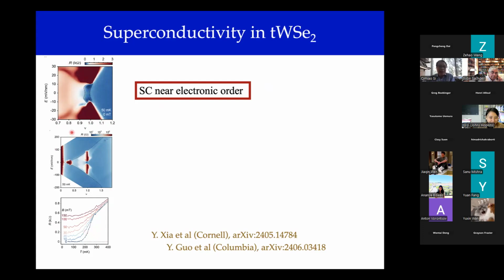And if you zoom out to a bigger phase diagram, so this is the superconductivity part of the phase diagram. These two blobs here are part of this half-filled, at least in the Cornell experiment, half-filled correlated phase. And there's a lot of discussion about Van Hove singularity, etc. At least by a certain way of tracing the Van Hove singularity, the superconductivity is not happening in close vicinity. In fact, it's far away from it. Now, so that's the observation of superconductivity.